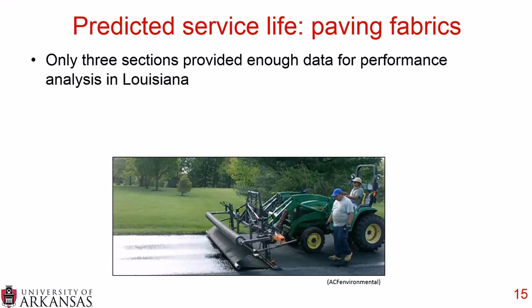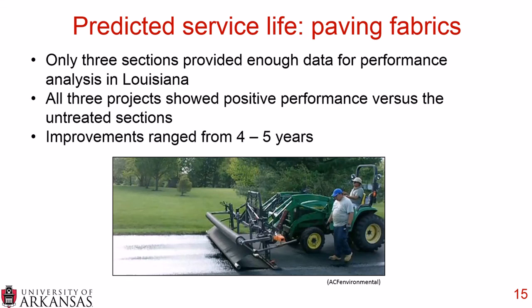So they first looked at paving fabrics, and when they were predicting the service life of various paving fabrics, they looked at 3 sections because only 3 sections provided enough data for performance analysis in this Louisiana study. And they found that all 3 projects showed a positive performance versus the untreated sections in this study, and the improvements ranged from delaying the reflective cracking anywhere from 4 to 5 years.